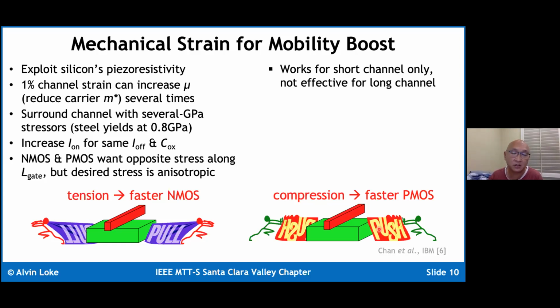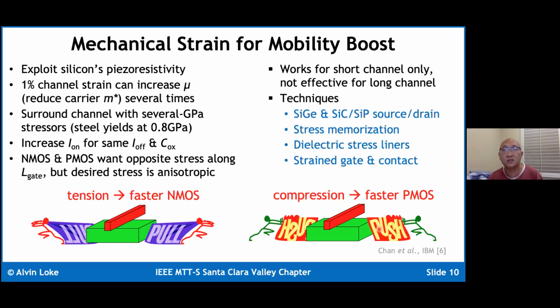And that's very simple to visualize, because you've got these source drain strain regions, typically they're under a lot of stress, and you've got a volume of silicon that's sandwiched in between that you're trying to compress or stretch, okay? So the longer the channel you have, the more volume of silicon you have to resist the surrounding pressure that's being exerted onto the transistor channel. Okay, and this is not good for analog transistors, because we typically need long channel devices for high output resistance. And so there are a host of different techniques that are used.